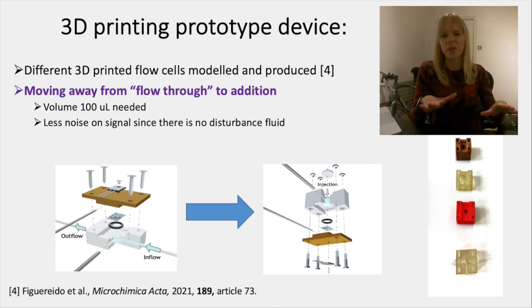If it was moving somewhat, you would see some interference in the thermocouples that we use for the thermal readings. And the advantage of using these prototype devices, sometimes we've made some devices in Perspex which are longer lasting, but particularly with 3D printing, you're able to develop disposable systems. And when you work with biomaterial or material that might contaminate something, it's very beneficial that you can throw away both the electrodes, because remember these were really disposable, cheap screen printed electrodes, but also dispose of the 3D printed setup and just use a fresh one every single time.